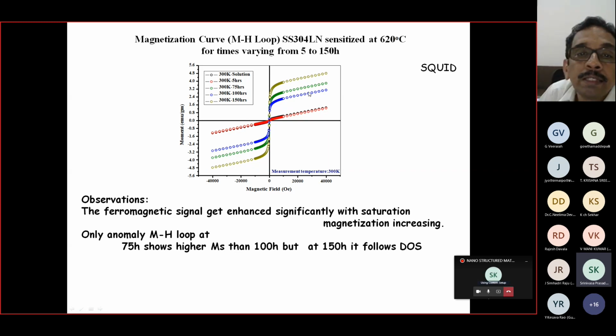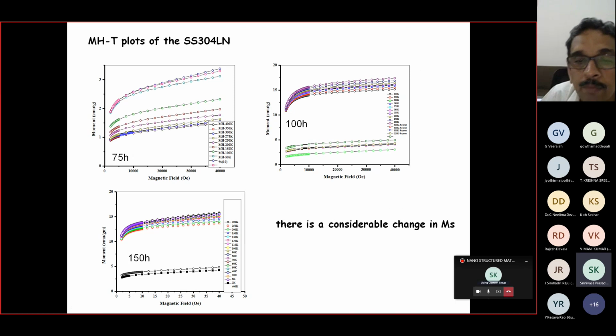So that means there is some transition occurring between these two times. We try to estimate that particular temperature through a technique called a vibrating sample magnetometer, where you can see on the y-axis the magnetic moment against the magnetic field. I am increasing the magnetic field to 40,000 oersteds, that is 4 Tesla, and measuring the magnetic moment of the sample under investigation.